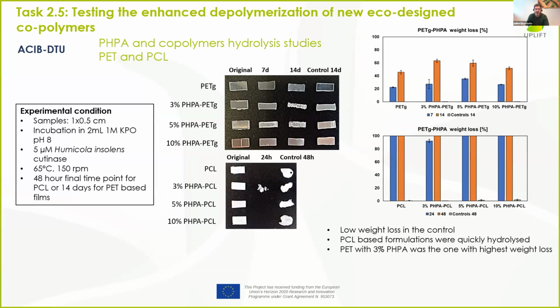Still, with the new eco-designed polymers, we basically had a copolymerization of PET and PCL. And as you can see from the picture, PET in the presence of 3% of PHPA has an enhanced degradation profile. For PCL, we know that it's a polyester that is easier to degrade, but in the presence of the copolymer, the degradation of PCL was even more enhanced. So therefore, this copolymerization, these eco-designed polymers, were improving the degradation in the enzymatic approach itself.